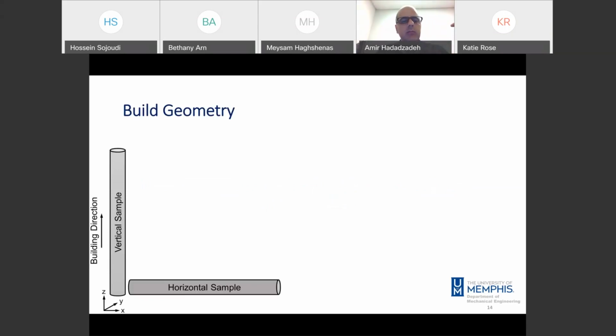So in this study, we fabricated two types of samples, two rod-shaped samples based on their orientation with respect to the building direction. We called them horizontal sample and vertical sample. The geometry of both samples was the same, but for the horizontal sample, the longitudinal axis of the sample was perpendicular to the building direction. And for the vertical sample, the longitudinal axis was parallel to the building direction. And we started